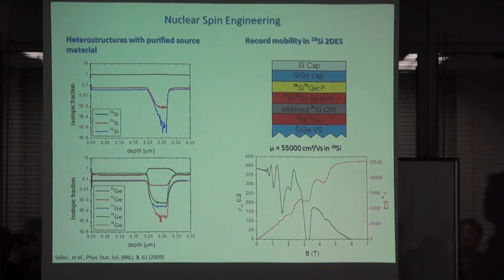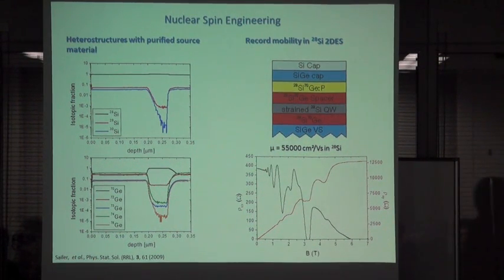And actually, in the moment, we have the best sample of isotope clean material with a mobility of 55,000, which is comparable to what you have with natural silicon. We were a little concerned if we really get high enough mobility, so Shubnikov-de Haas oscillations start at about 0.5 Tesla, which gives you this kind of mobility in silicon-28.